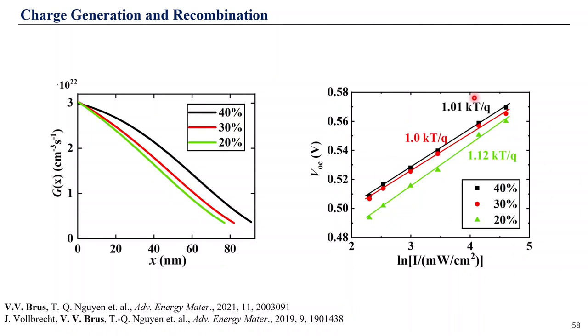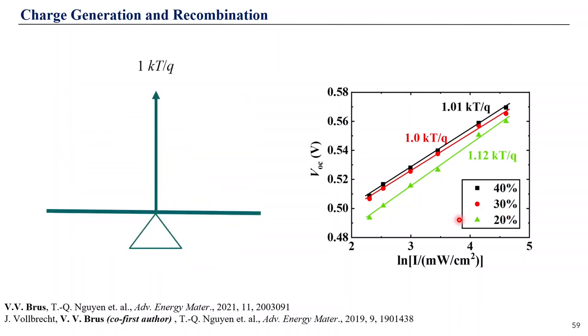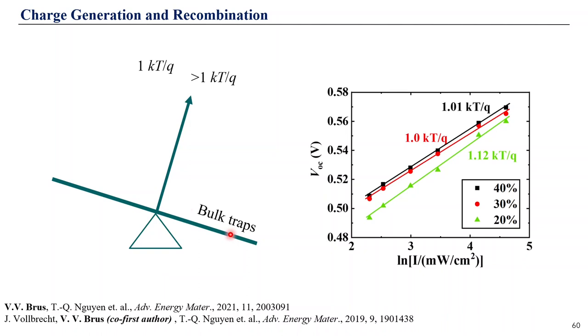So first, we look at recombination, which we probe when we measure VOC versus light intensity and check the slope in terms of kT over q. So we see that for 40 and 30%, the slopes are close to unity, 1 kT over q, and a slight increase once we go to 20%. The slope of 1 kT over q corresponds to pure bimolecular recombination. However, if there is an increase in relative contribution from bulk trap-assisted recombination, the slope becomes larger than 1 kT over q. That's something we can see here.